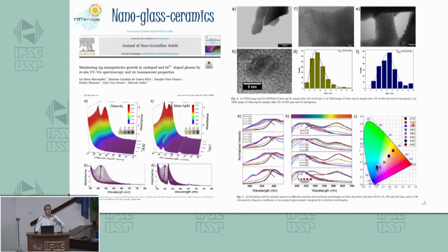Otherwise we need to treat the glass in the furnace, take it out, do the measurement, put it again into the furnace, take it out, do it again, and in this case we do the treatment inside the equipment. We did some treatments for 72 hours because for some glasses the crystallization was very, very slow, and so we can do that using this approach.